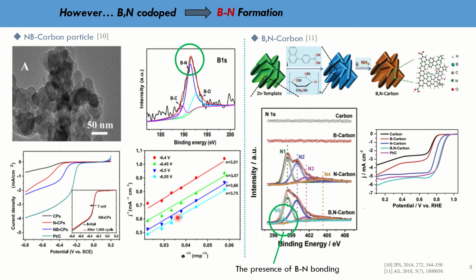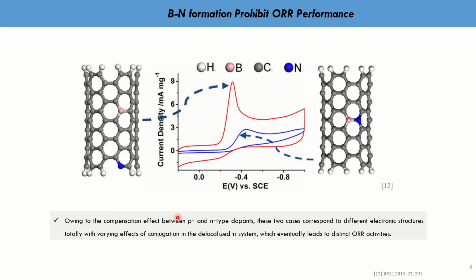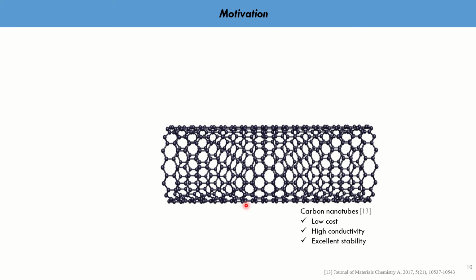However, boron-nitrogen co-doped materials have B-N bond formation, which is unfavorable for ORR activity owing to the compensation effect between P- and N-type dopants. These 2 cases correspond to totally different electronic structures with varying conjugation effects in a delocalized pi system, which eventually leads to distinct ORR activities.